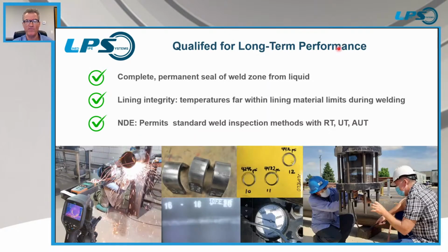This is a little bit of information on our long-term performance. You'll see here in a minute a hydrostatic pressure test in Brazil, which shows that our innovative seal design completely seals off the weld zone from liquid at any pressure. It actually utilizes the pipeline pressure to achieve a seal. So the higher the pipeline pressure, the tighter the seal. That's one of the most important parts. There's other technologies out there that really can't do that.